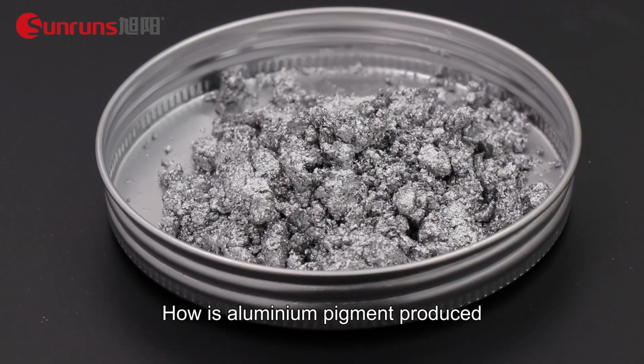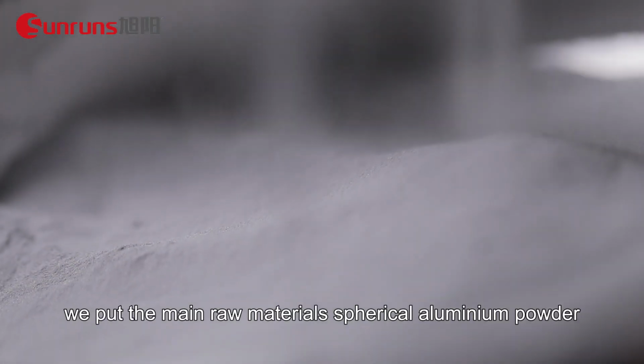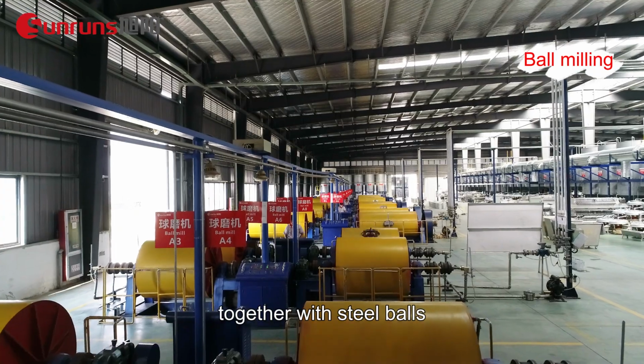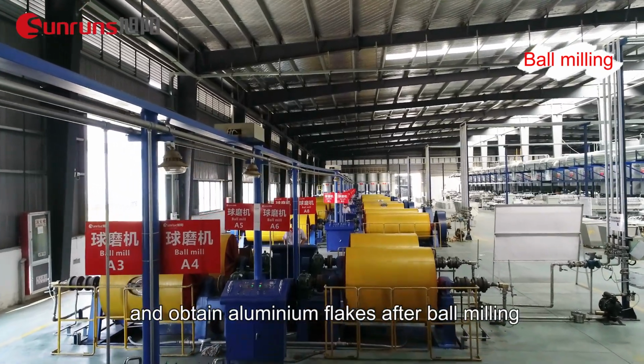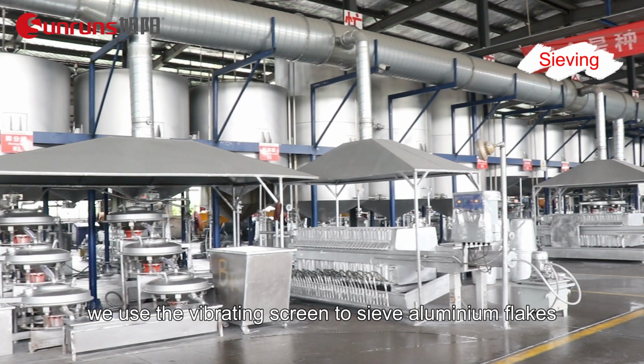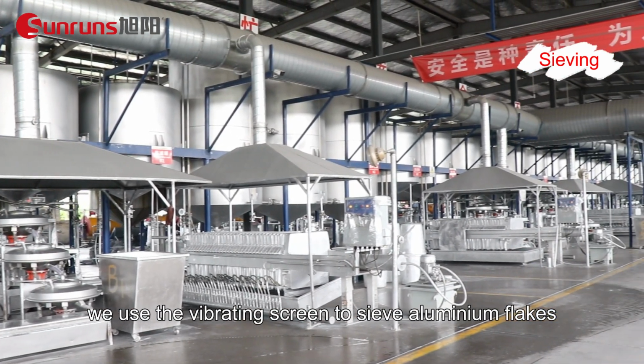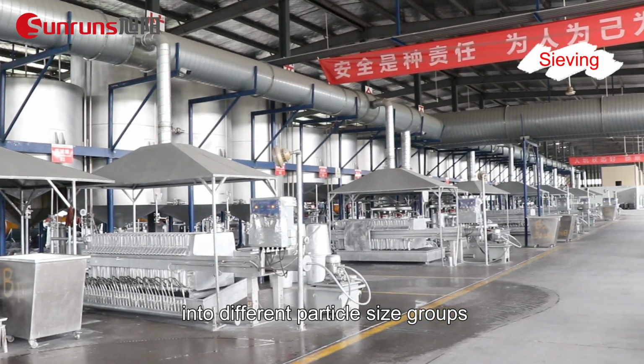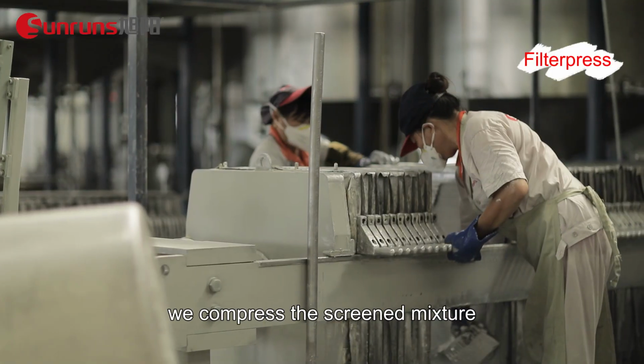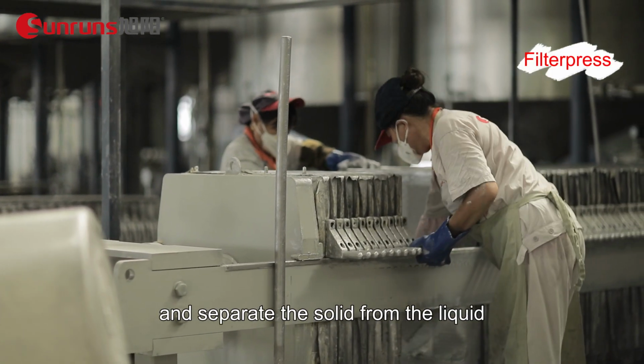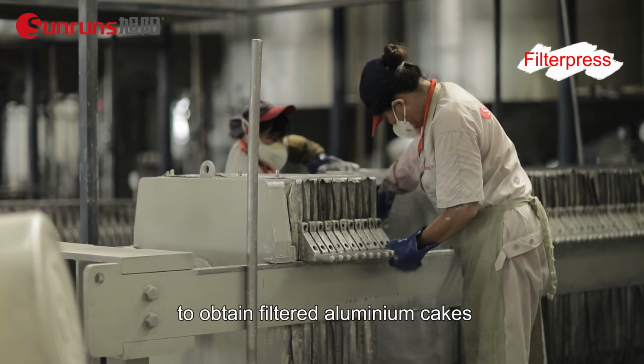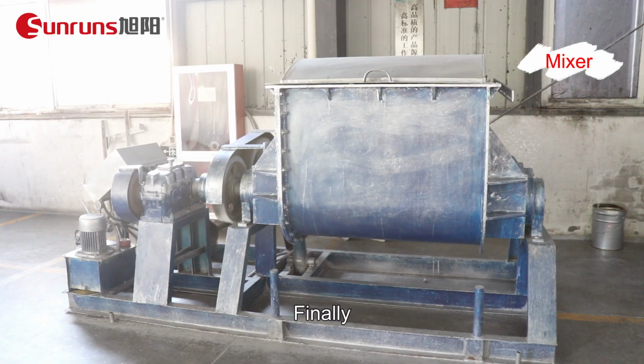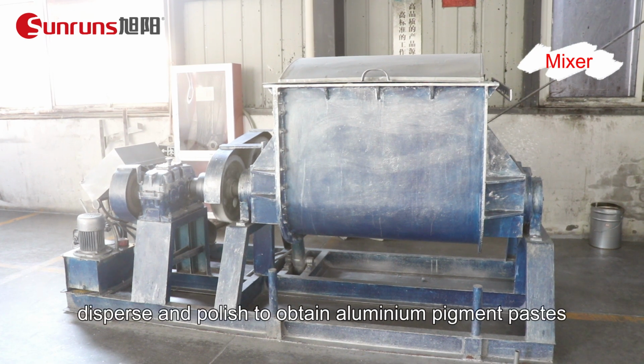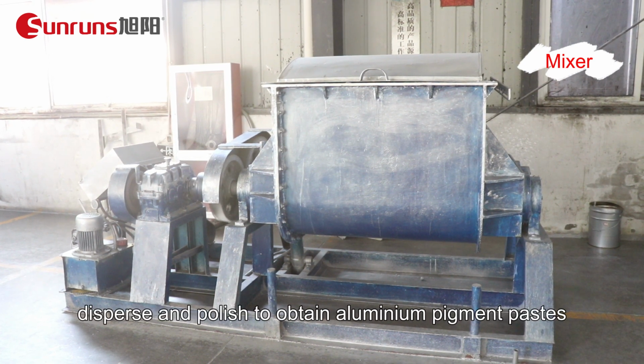How is aluminum pigment produced? Firstly, we put the main raw materials, spherical aluminum powder, solvents, grinding aids, and additives into the ball mill, together with steel balls, and obtain aluminum flakes after ball milling. Secondly, we use the vibrating screen to sieve aluminum flakes into different particle size groups. Then, we compress the screened mixture and separate the solid from the liquid to obtain filtered aluminum cakes. Finally, we use the blender to mix, disperse, and polish to obtain aluminum pigment paste.